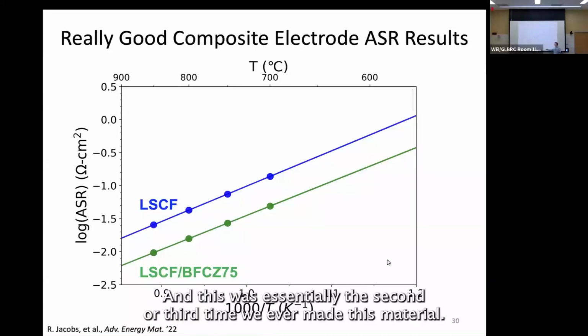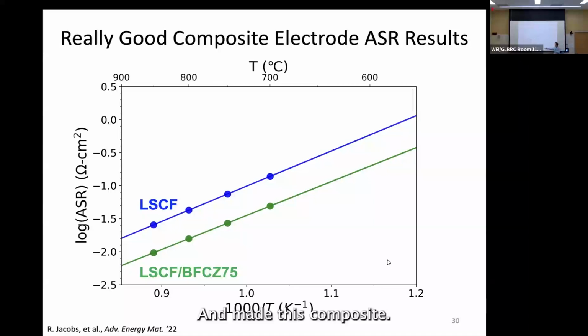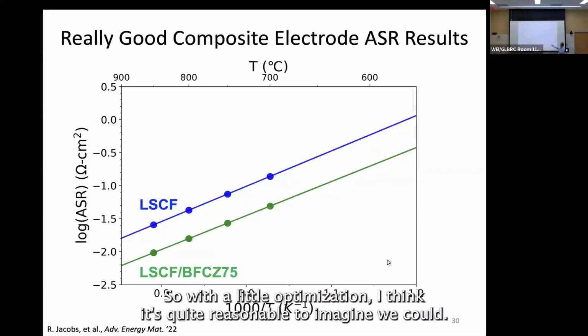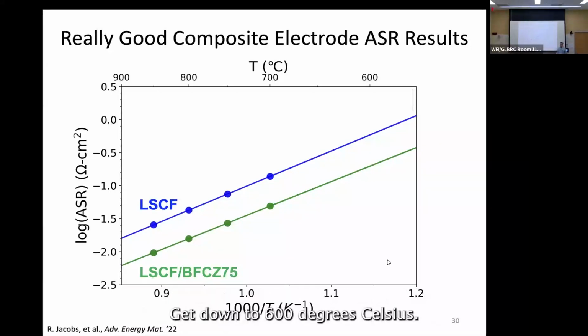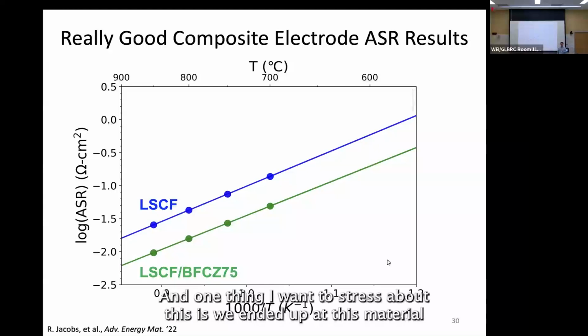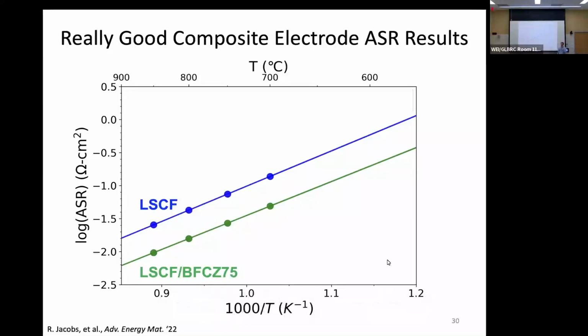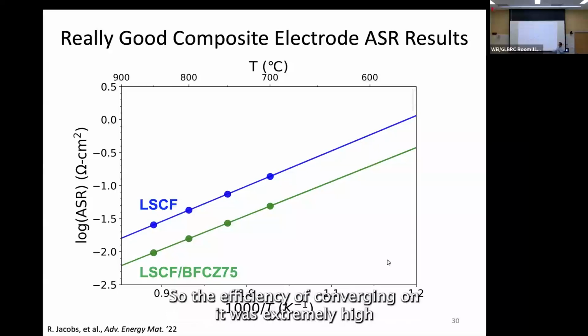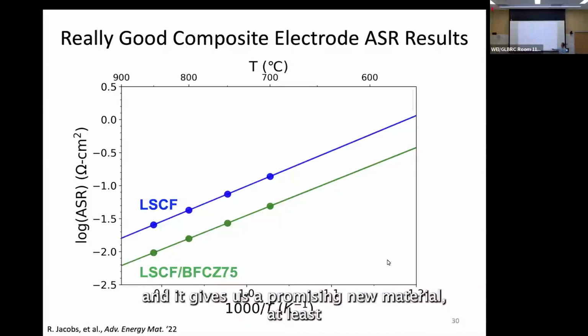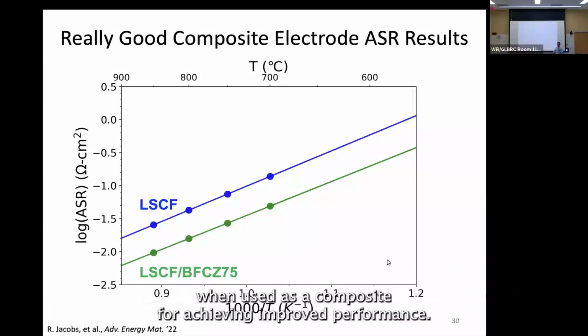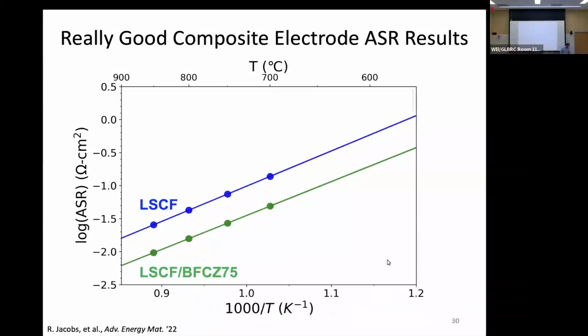And this was essentially the second or third time we ever made this material and made this composite. So with a little optimization, I think it's quite reasonable to imagine we could get down to 600 degrees Celsius. We just haven't gone through that process yet. So this was an encouraging result. One thing I want to stress is we ended up at this material with a few tries after the whole computational screening process. So the efficiency of converging on it was extremely high. And it gives us a promising new material, at least when used as a composite, for achieving improved performance.